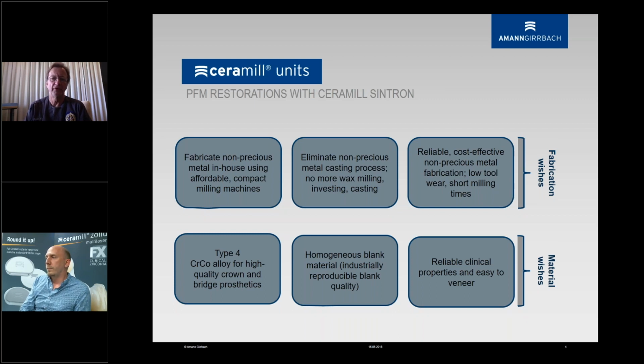Most chrome alloys, if you degas ahead of time, and I may not use the right terminology, but it's like the oxide, when it has a head start, tries to grow through the opaque. Now, some of the old chrome that we used that was milled from other companies way back that we were applying porcelain to, like for big bar cases and stuff like that, first thing we did was degas them. And then we'd put 3, 4, and 5 coats of opaque on,